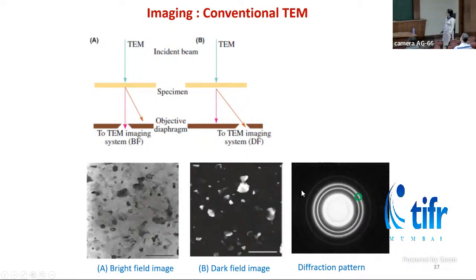The dark field image can give us information about the Z number of the sample, and this is the diffraction pattern which we get from a polycrystalline sample. The diffraction patterns are formed in the back focal plane of the sample. So if you put an aperture across one particular ring, then it can highlight the crystallites in that particular plane. So this is the information we can get from dark field imaging.